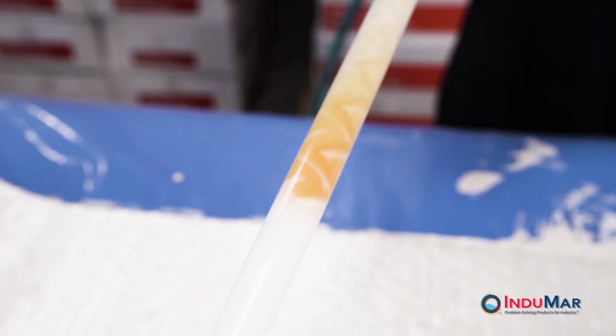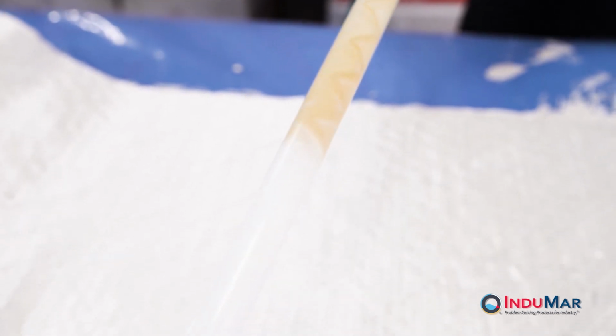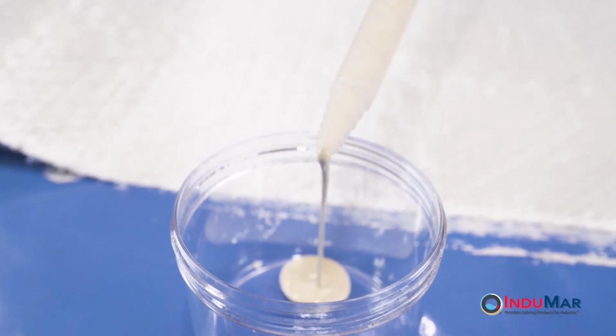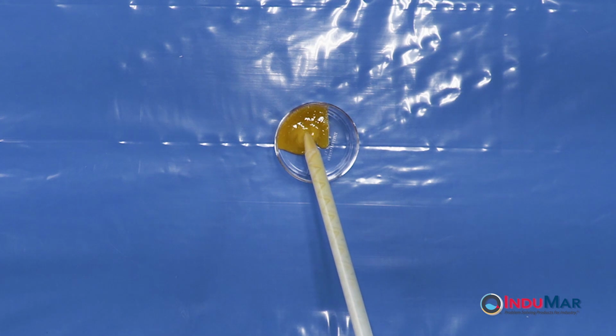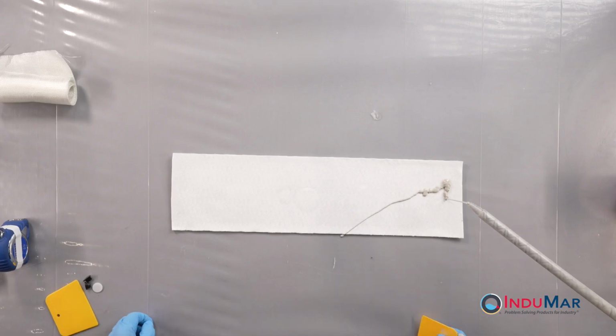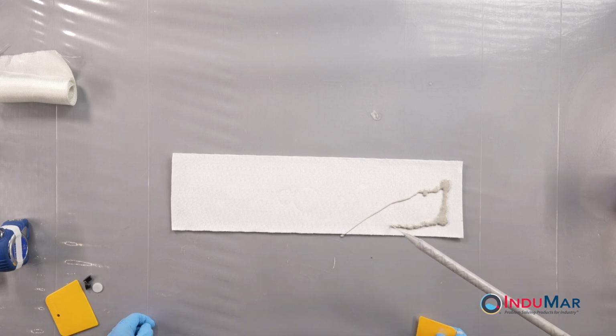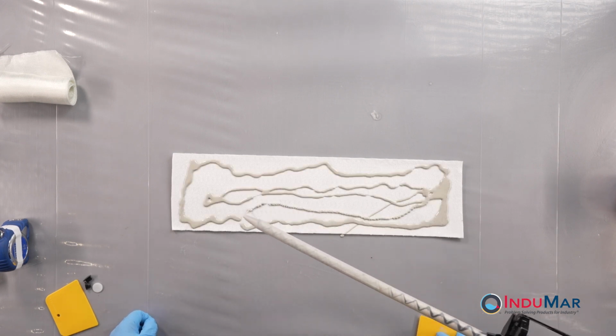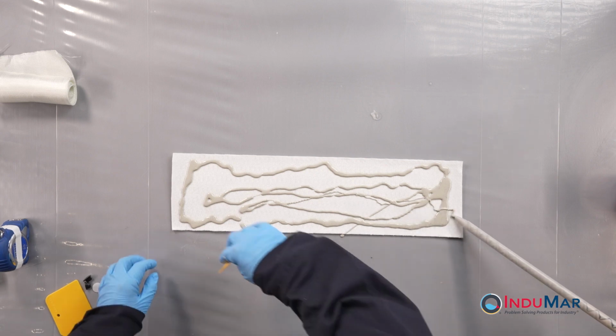Slowly dispense resin from the cartridge, filling the static mixer. Once filled, dispense about 50 milliliters or about 1/4 cup of resin into a waste container to achieve complete mixing within the nozzle. Once the epoxy cartridge has been prepared, apply resin to both sides of the technical felt according to the loading described in the written instructions.